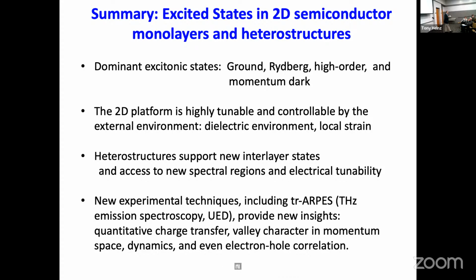I'm really interested, particularly about biexcitons. Is there any experimental evidence that there is a correlation in the emission of the two photons? So the question was, have people really seen correlated emission of photons from biexcitons. I believe there's one paper, it has not been studied extensively. You would certainly need to be in a regime where you have high quantum efficiency, otherwise the whole thing will be very painful experimentally. And there's been steady progress, and early on the quantum efficiencies were really not that high, maybe 1% or something. Now there are a lot of reports that it's close to 100% if you do the right things. So it would be very interesting to go back to that issue.